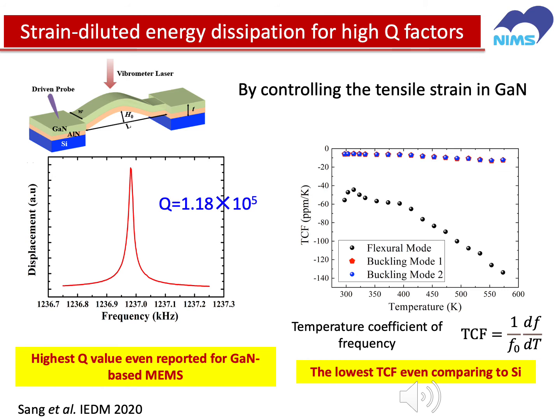Here we used the gallium nitride on silicon technology to fabricate the MEMS resonator. The resonator has a double-clamped beam bridge structure, and by releasing the silicon substrate, we can obtain the MEMS device. The performance of the MEMS is improved by modulating the tensile strain in the gallium nitride. We find that the strain can dilute the energy dissipation in the resonator, and greatly enhance the quality factor of the resonator. The highest one we can achieve is more than 10^5. This value is also the highest ever reported for gallium nitride MEMS, and it is much higher than for gallium nitride HEMT resonators.